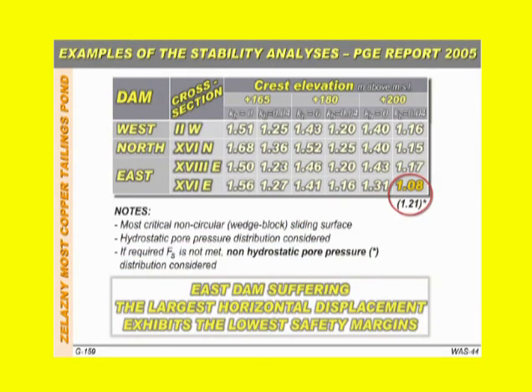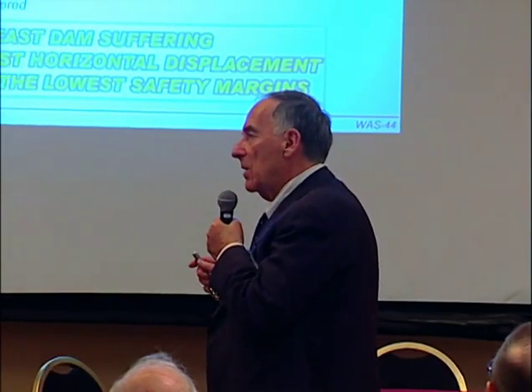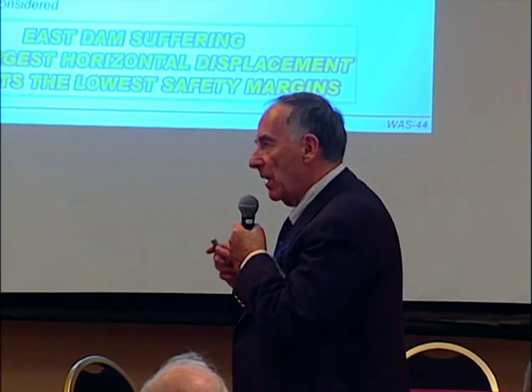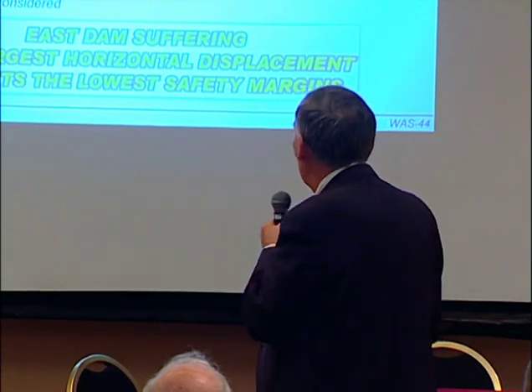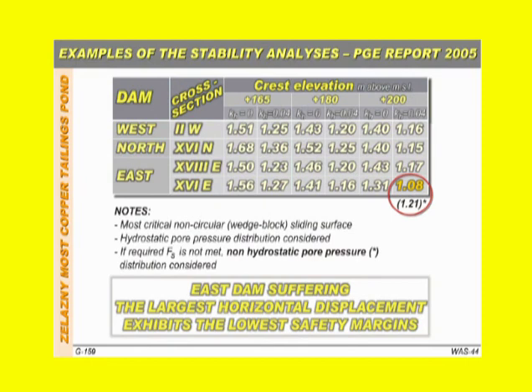The next, here you have an example of different cross-sections with the mining-induced seismicity and without mining-induced seismicity. And when we go below, this is unfortunately the East Dam, the one which is moving too much, with too low a safety factor with the induced seismicity. We are going to examine the local piezometers and the local groundwater condition, which unfortunately are changing with time, because the tailings pond is a very strange geotechnical structure in which the boundary condition and initial condition are continuously changing with time. And in this case, taking appropriately the piezometric head, we obtain 1.21 instead of 1.08.